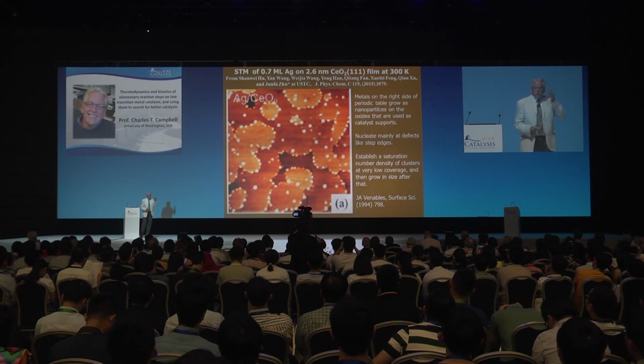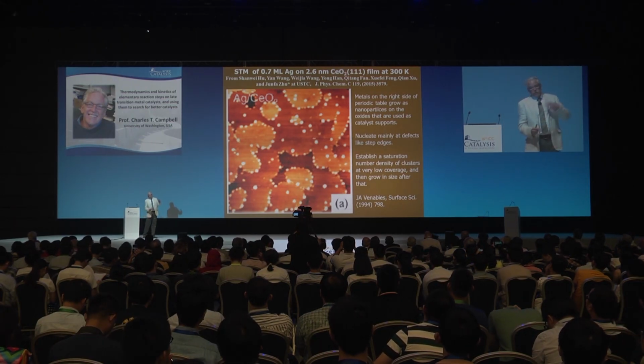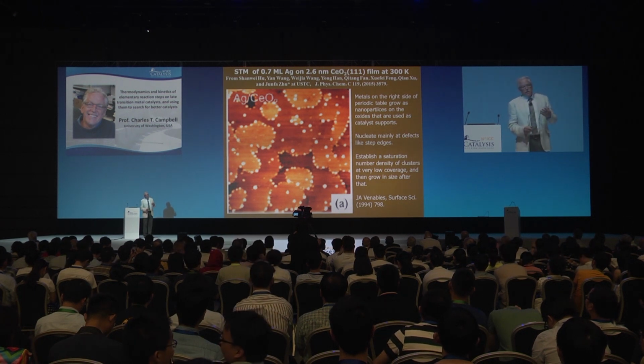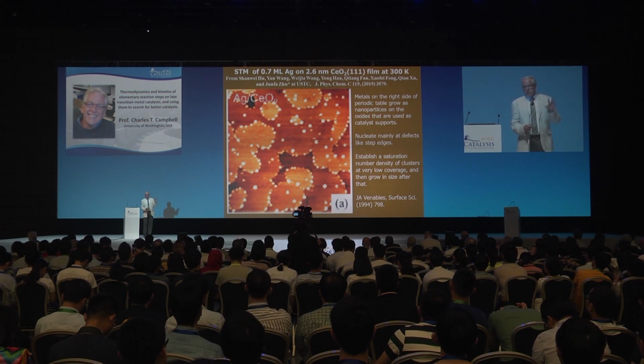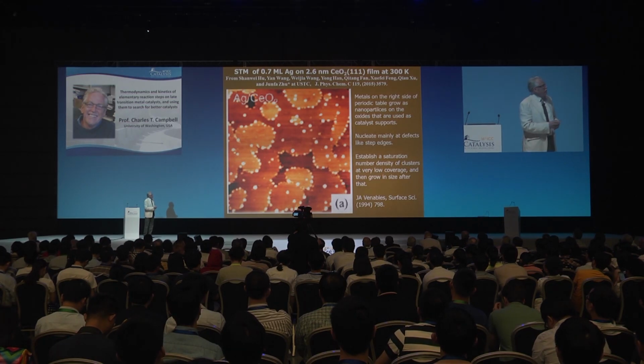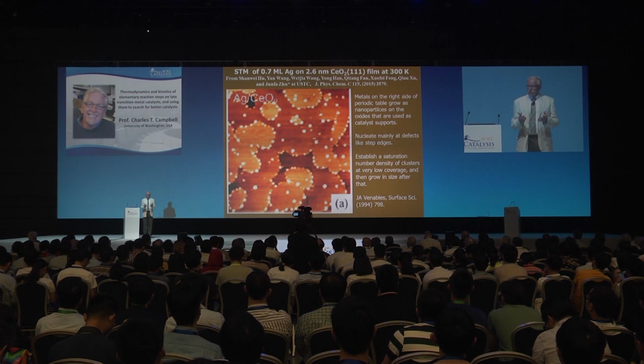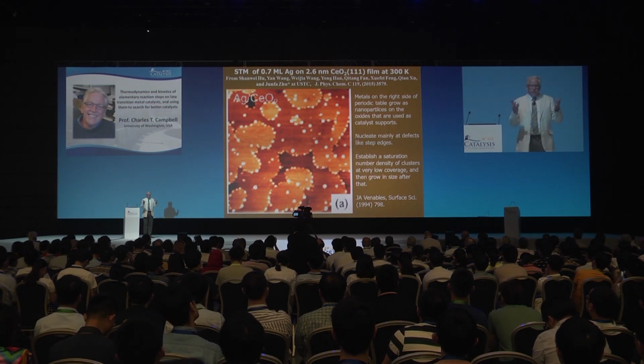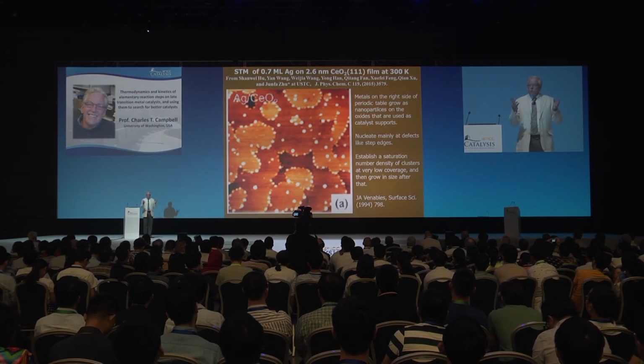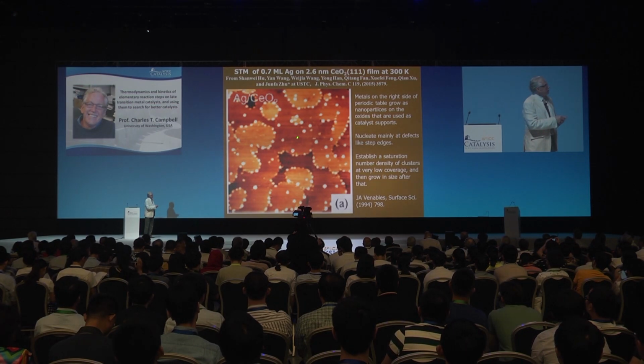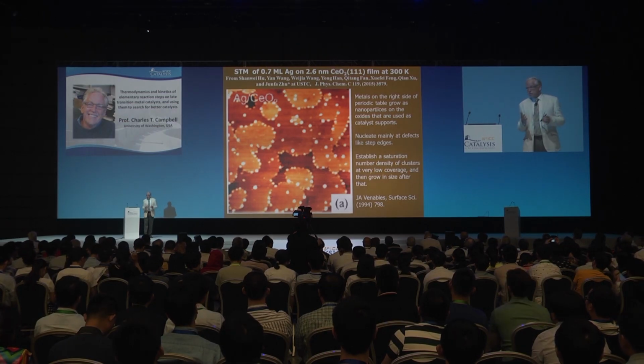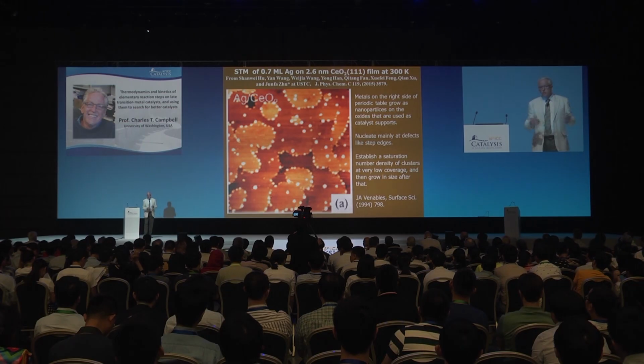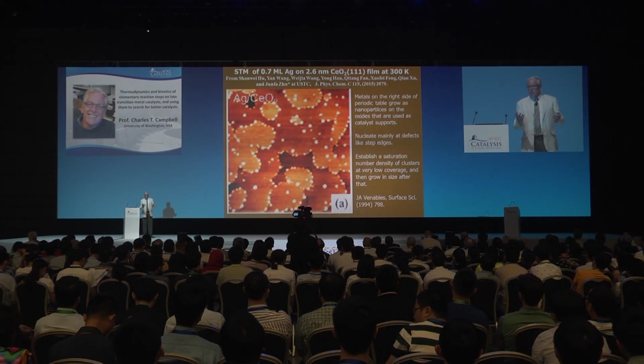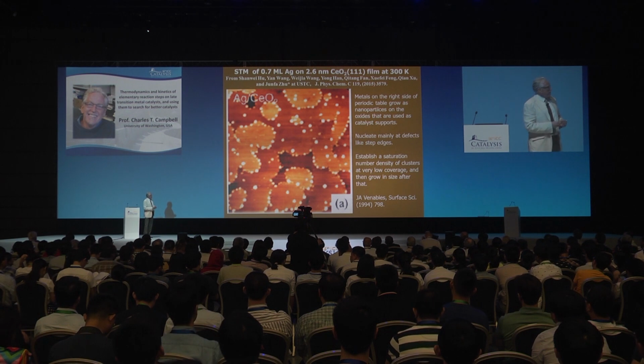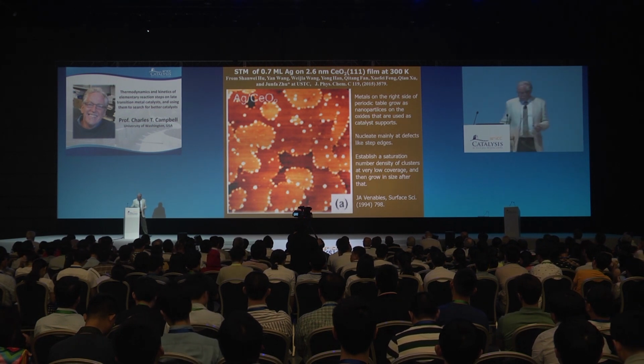And a few important points about the way these particles grow. When you evaporate a metal onto an oxide, they go through a nucleation stage in the first about 1% of a monolayer, and they grow clusters. And after those clusters form, as you go up in coverage after that, the number of clusters doesn't change. The individual particles just grow in size, and that's because metal atoms land on the surface and they migrate around and they find an existing cluster to add to. So we can control the average particle size by just controlling the amount of metal that we've added to the surface after about the first 1% of a monolayer.